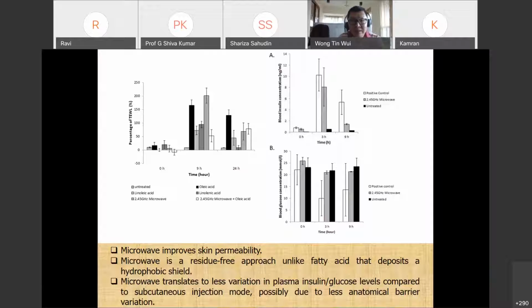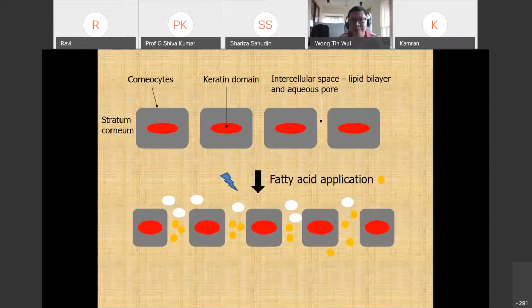This is further illustrated through a transepidermal water loss experiment. In this experiment, treating the skin with microwave is accompanied by a high level of transepidermal water loss. So the microwave can actually improve the skin permeability. And more importantly, compared to fatty acid, microwave is a residual-free approach, unlike fatty acid, which deposits a hydrophobic shield, which is highly unfavorable for skin transport of insulin.